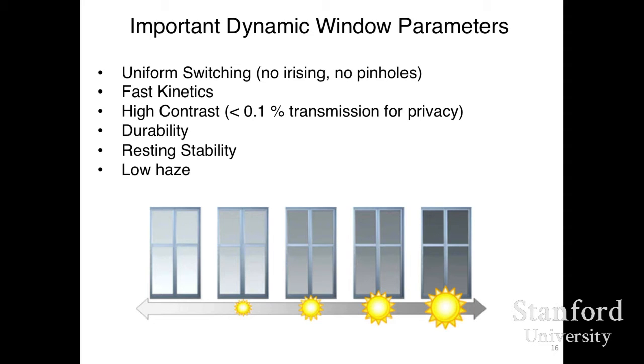So just to highlight some of the needs here for windows technology, it needs to have uniform switching. And I should elaborate that a lot of the technologies work well when they're small, but it's hard to make a large window switch fast. The reason is that when the window's large, it's drawing a large amount of current. And when that current goes through the transparent electrode, there's a voltage drop just due to Ohm's law. And then the switching depends on the voltage. And so the windows switch faster on the edges where the voltage is high, and slower in the center. And that leads to an effect called irising. So probably better electrodes are needed, or windows that switch with a lower current.